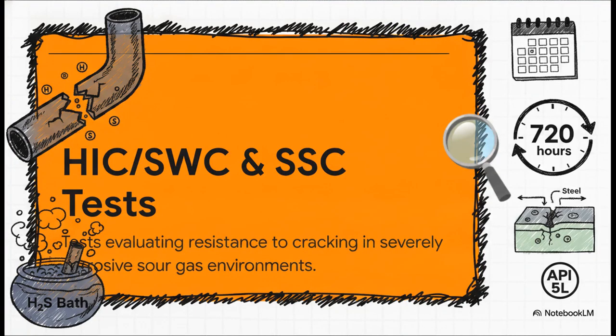Now, when pipes transport sour gas, the chemical attack they face is just relentless. Our main enemies here are hydrogen-induced cracking and sulfide stress cracking. To fight this off, these grueling 720-hour tests are absolutely mandatory. Just imagine putting stressed steel into a bath saturated with chemically pure hydrogen sulfide for 30 days straight. It's intense, but it ensures hydrogen atoms don't blister the steel and snap the pipe under pressure.